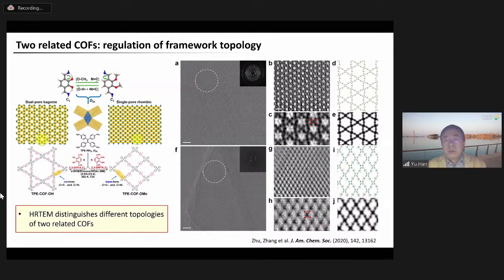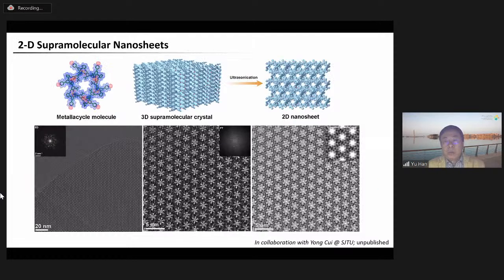And this example is 2D nanosheets which are exfoliated from 3-dimensional supramolecular crystals. This is not MOF, not COF, but a supramolecular structure. After exfoliation, due to the very low yield of the nanosheets, it's difficult to characterize their structures, and conventional TEM didn't show any structure information because of the beam damage issue. With our low dose TEM, we confirm that these 2D nanosheets retain the original structure ordering in the parent 3D crystals.